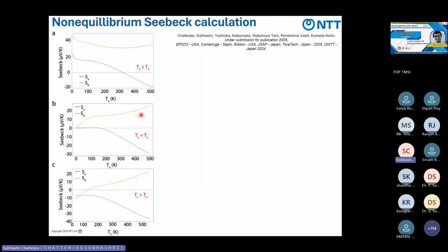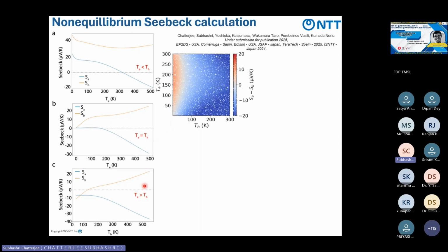We calculate this along SA and SB by taking care of three different conditions: when the electron temperature is higher than the hole temperature, the isothermal case where they're equal, and when the electron temperature is lower than the hole temperature. Comparing all three, if we do SA minus SB, just simple math, at 300 K,